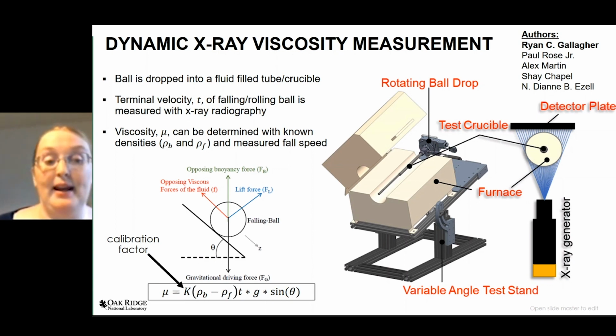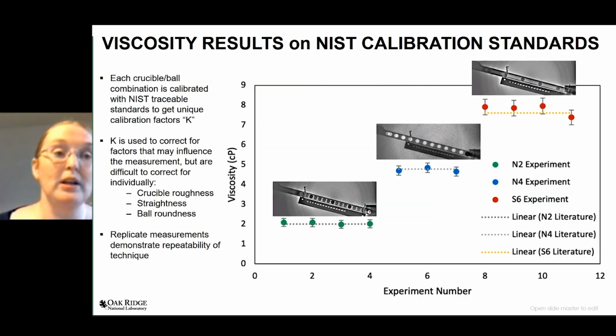Important to note here is that calibration factor K. So each crucible and ball combination is calibrated with NIST standards to obtain that K calibration factor. And that is used to correct for factors that may influence the measurement, but are difficult to correct for individually, like crucible roughness, the straightness of the tube, the ball roundness, which is why it is essential to obtain that K for each ball crucible combination. And of course, Oak Ridge is making replicate measurements to demonstrate the repeatability of the technique. And you can see that here, they've used 3 NIST calibration standards and made replicate measurements and are showing good